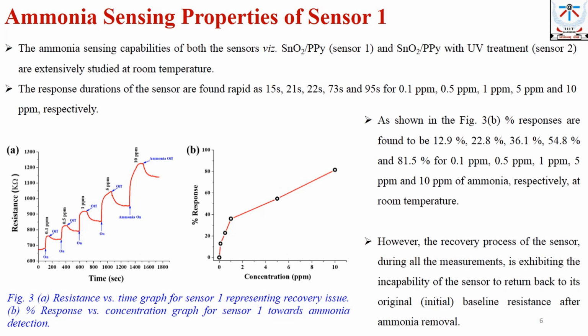However, the recovery process of the sensor during all the measurements exhibits the incapability of the sensor to return back to its original baseline resistance after the ammonia removal, which shows the baseline instability of sensor S1. This recovery issue may exist due to the lack of protonation of nitrogen in polypyrrole during desorption of the ammonia. This staircase response of sensor S1 represents the non-suitability of the sensor for